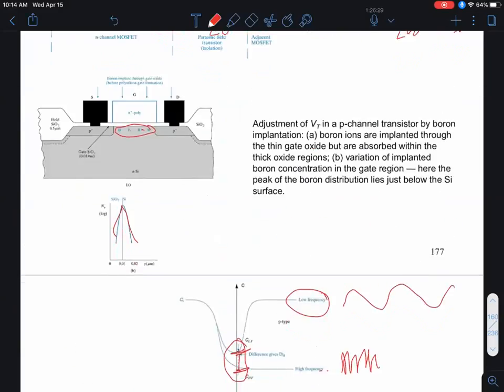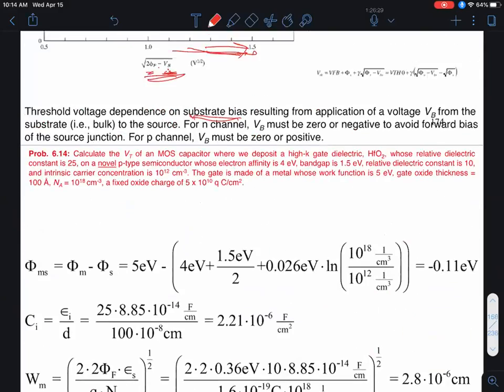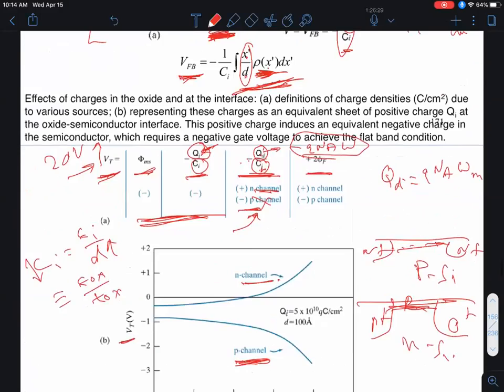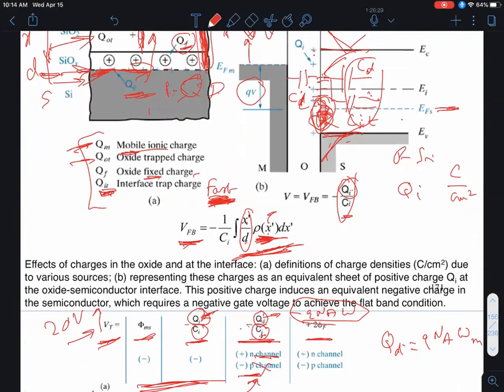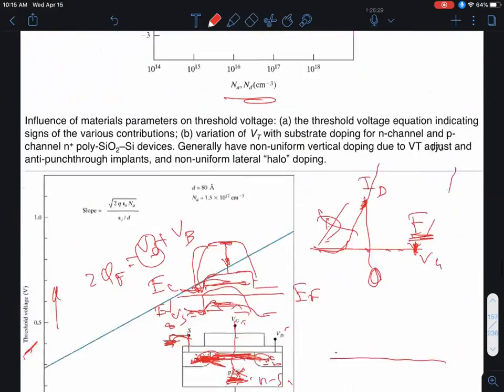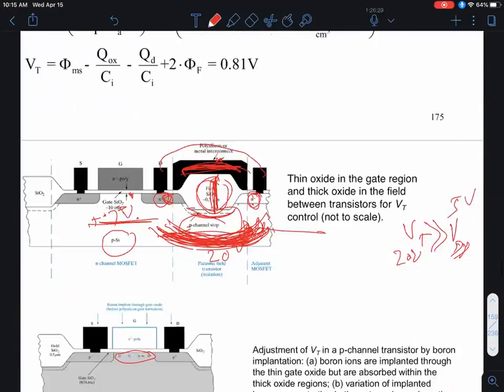So that's why you have to do this weighted sum in terms of figuring out the impact of these charges on the flat band voltage. Remember that? So the point is, for the mobile charges, this rho of x is not constant. As they move back and forth, this rho of x varies. Therefore, the flat band voltage would vary, which is a huge reliability problem. Okay? And that is measured by the so-called bias temperature stress measurement.